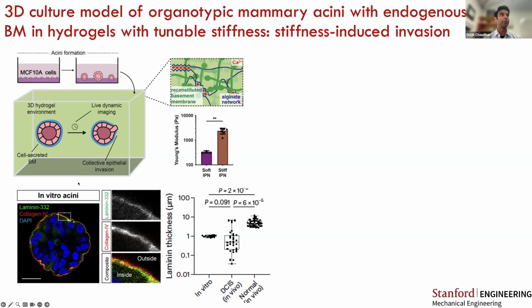So that you can see on the bottom panels here, where we stain for laminin 332 and type 4 collagen, two key components of the basement membrane. And we see the layering with laminin on the inside, collagen 4 on the outside that we expect of basement membrane. And importantly, the thickness of the laminin that we see in our in vitro model matches what we see in pre-invasive breast cancer, or ductal carcinoma in situ, but it's a little bit thinner than what we see in normal tissues. But of course, we're trying to capture this invasive breast carcinoma condition.